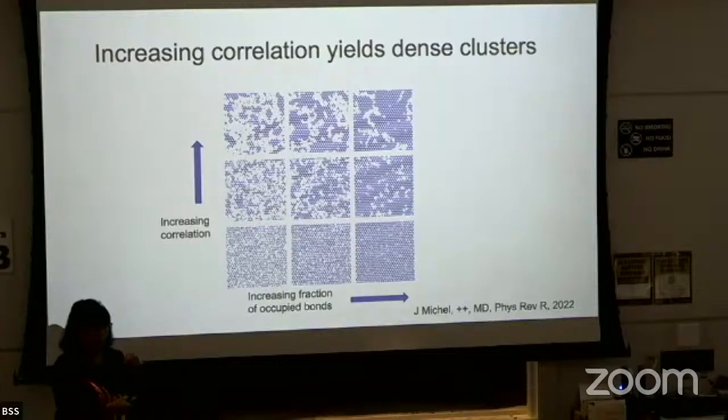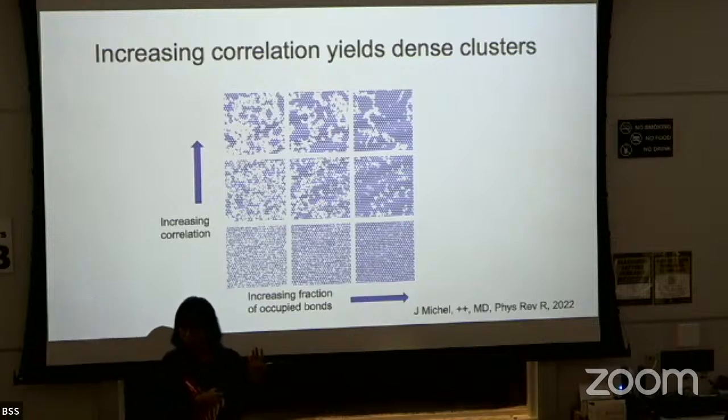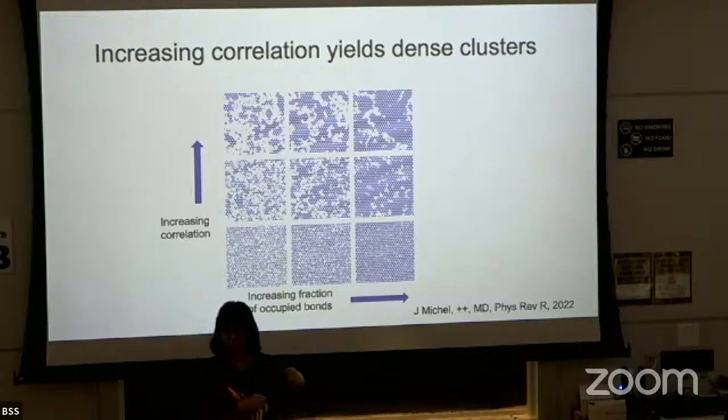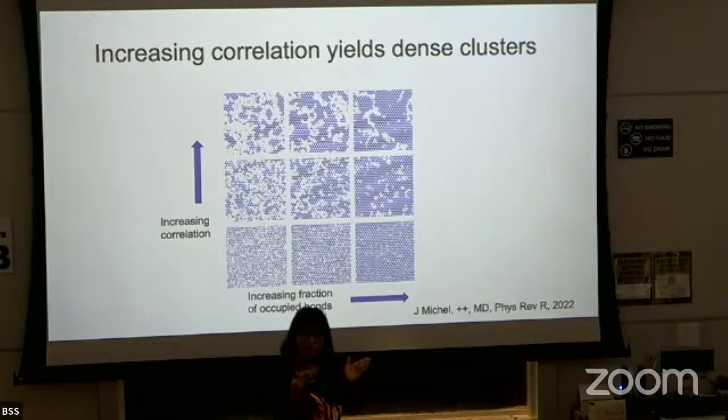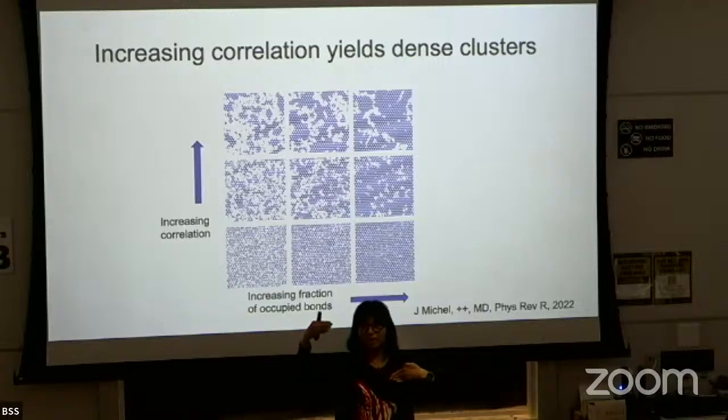So then we wanted to find out what would be the shear modulus for these kinds of networks. Doing this calculation with an effective medium theory is much harder. So we did an energy minimization, like I was telling you. Once again, we write down the deformation energy for this thing, and then we apply, let's say, a small shear. We minimize the energy, and then we can calculate, in the linear regime, the shear modulus, which is basically 2 times the energy density divided by the square of the strain, etc.